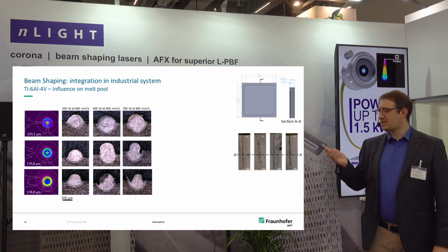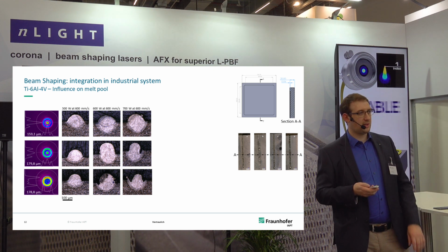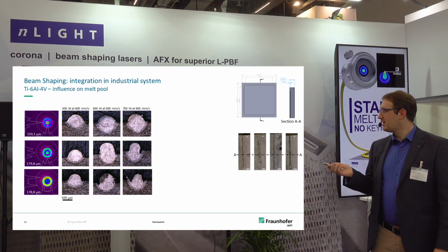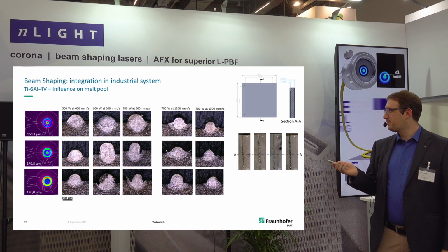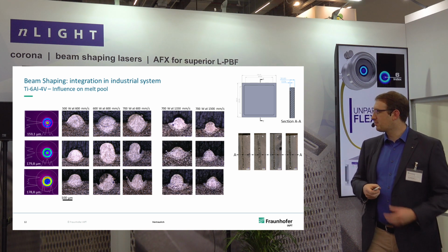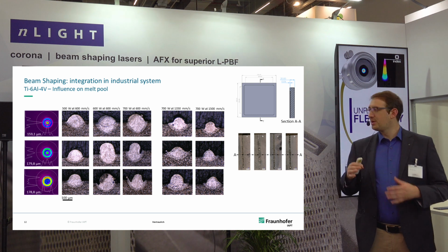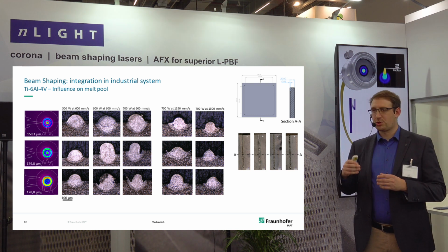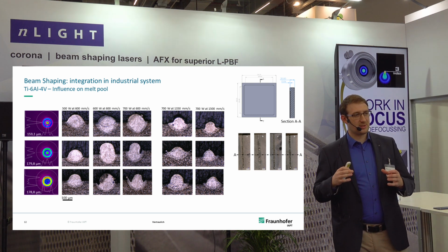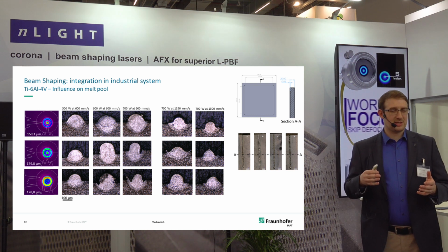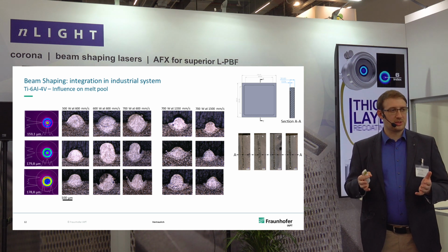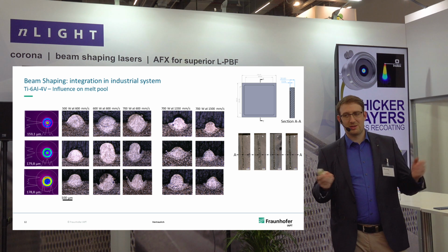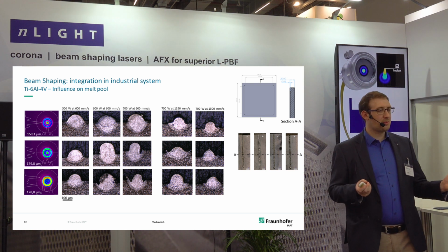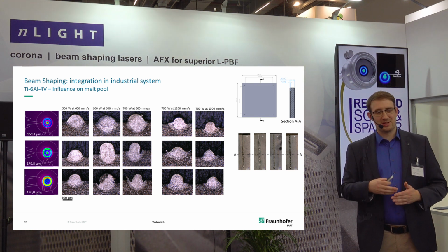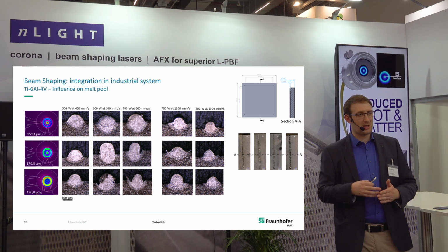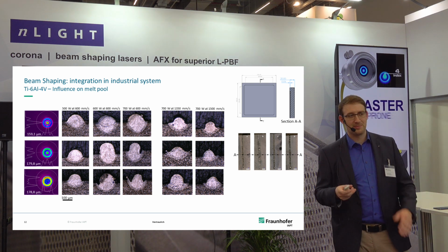Now, of course, 600 millimeters per second is quite slow in L-PBF processes. So if we increase the scan speed, still using 700 watts, we noticed that the protrusion effect decreases. But of course, on the other side, the melt pool also decreases. So this is like a perfect optimization problem: where's the process where we can find the most stable process, the fastest process?